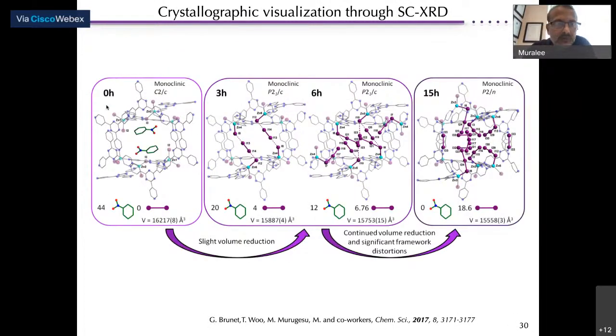And that's what we were able to do: after 0 hours of exposure, this is the original MOF, and then 3 hours exposure, 6 hours exposure, and 15 hours exposure. Just to tell you, this is 6 months of work of X-ray data. Each one of them we collected at least 5 times on different diffractometers to make sure what we are seeing is not an artifact. And we can clearly see that after 3 hours, the MOF itself has these iodine anchors